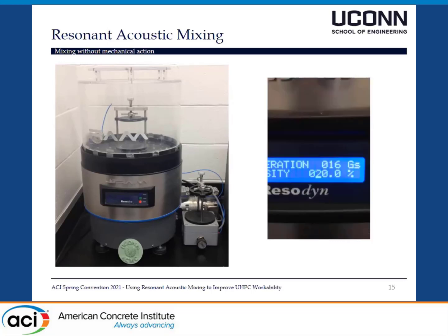looking at video quality of mixing. So a visualization of the mixing process is also another way to quality control mixing. So right at this instant, you can see that the mixture has mixed. And if you're wondering about all that liquid that was on top of the mix, that's actually not water, that was heptane, because this particular UHPC mix was UHPC with a heptane carbon nanofiber emulsion. And since heptane is hydrophobic, it doesn't mix with cement, and so it gets released outside the cement, leaving the carbon nanofibers inside the UHPC. So yeah, we can mix UHPC, but now does it give good results?